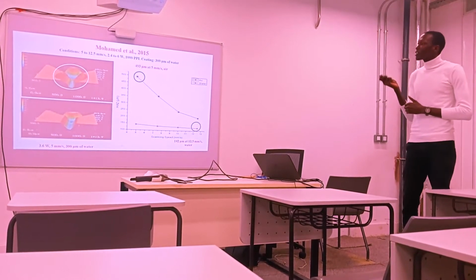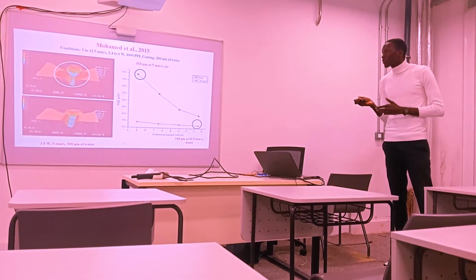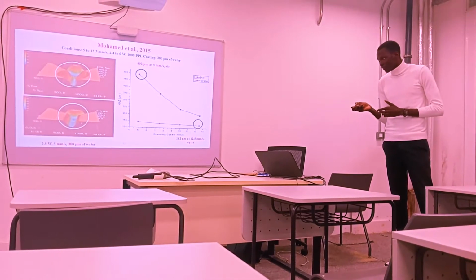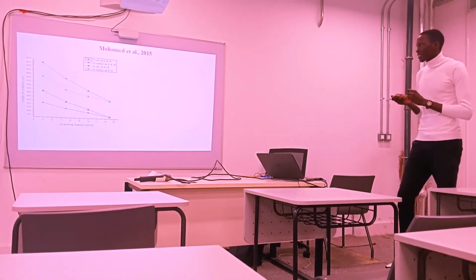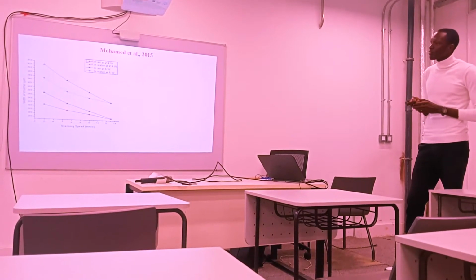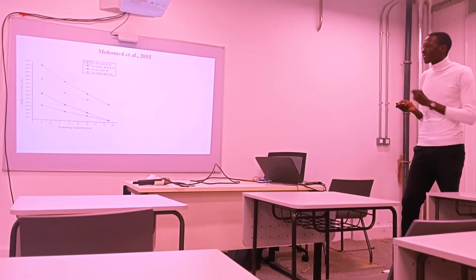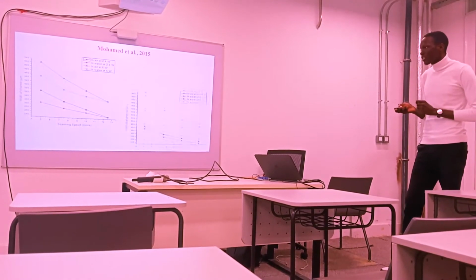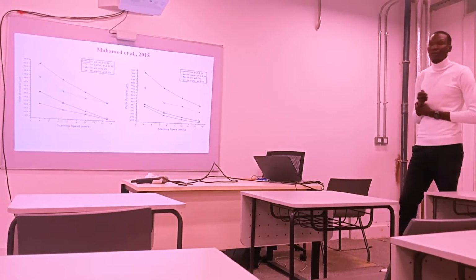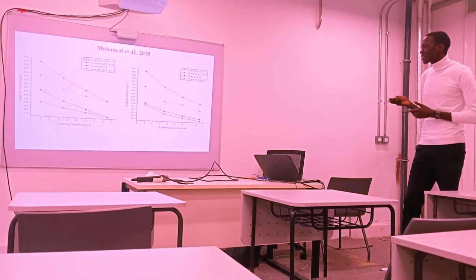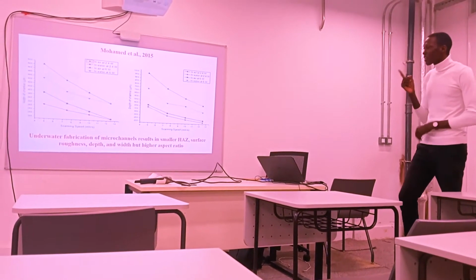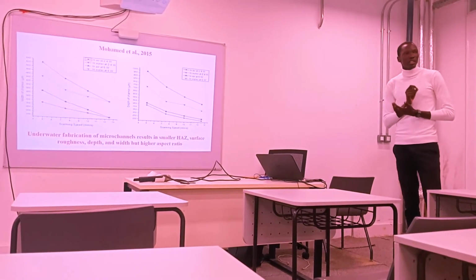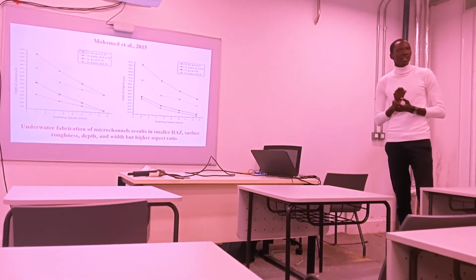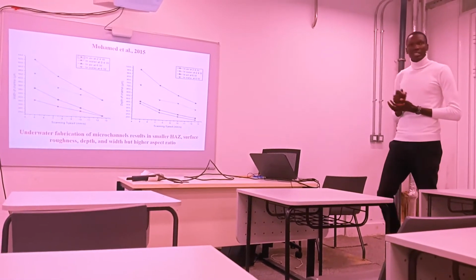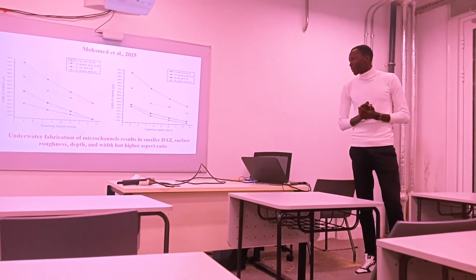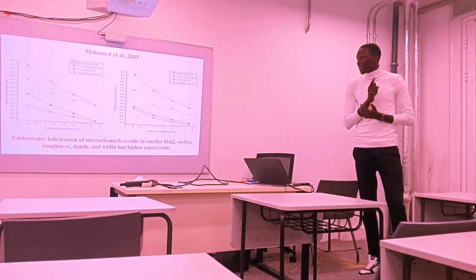As we can see, the microchannel in air is not so good compared to the one in water. Now, this is the plot of the microchannel width against the scanning speed in water and in air combined. So they concluded that underwater fabrication of microchannels results in smaller heat affected zone, smaller surface roughness, smaller depth, and smaller width, but high aspect ratio.